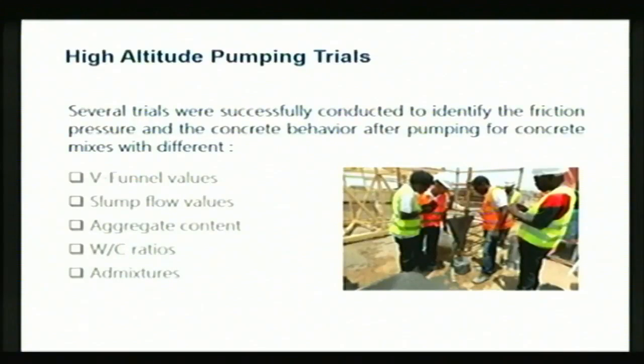We even had to look at the pump pressure. We found out that anything above 200 bar on the pump will not take the concrete up there. So we had to reduce the pump pressure below 200 bar, and we worked that out by first taking the pump away from the first elbow. So you have a horizontal distance, which is 25% of the vertical distance, that you should maintain. And then we also gave some slope to the initial horizontal outlet of the pump to make sure the back pressure on the pump is not very high. So when you pump the concrete and the concrete is going back, it doesn't really add to the pump pressure.